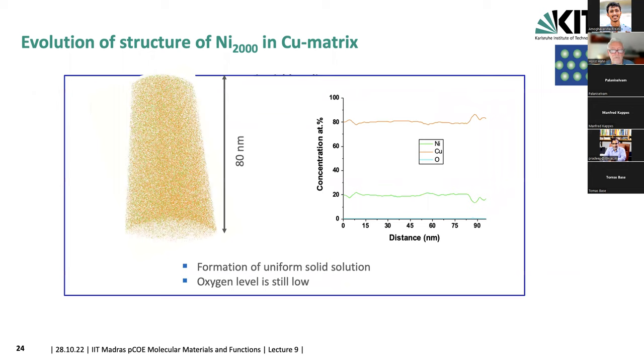So now we look at the structure after we have interdiffused it at 450, and we see we have formed a solid solution, very uniform, random, and the oxygen level is still very low. You see that on the right graph at the line, which is basically at the x-axis, and you see that the nickel and copper is basically homogeneously distributed. So over the entire sample or film thickness, all this was fully dissolved.